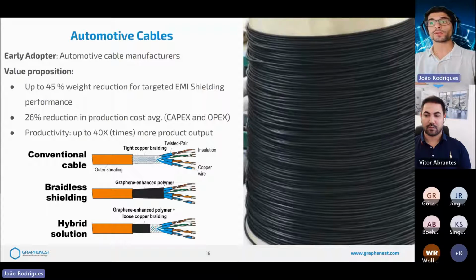And this works very well to shield at low frequency ranges. But for the high frequency ranges, you can use a graphene enhanced polymer jacket, and this combined solution will work very well overall in the entire frequency range of operations. So you have the best of both worlds with the metal and also the graphene polymer.